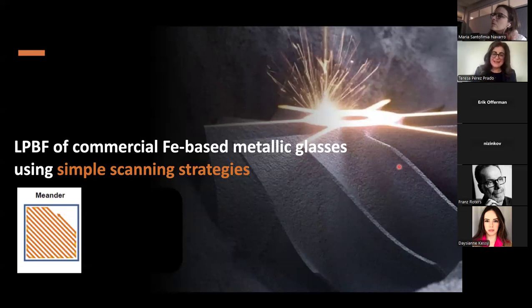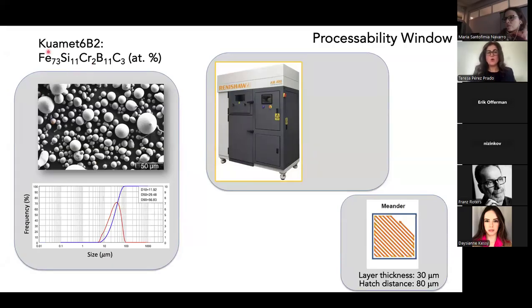So we thought, let us start understanding well the fundamentals, what are the relationships between the LPBF processing parameters, the structures of the printed parts, and the properties. And we start with a simple scanning strategy, just to understand the basics. And by simple, I mean this meander scanning strategy. So just back and forth with the laser, and let's see how far we can go with this strategy and with the commercial alloys. So we worked in parallel with this alloy Kuamet. You can see the composition here, iron, silicon, chromium, boron, carbon, and Finemet. Most of the slides of the results I'm going to show you are related to Kuamet because actually they behave very, very similarly. I'll show just some scattered slides about Finemet, but basically the storyline is the same for both alloys.